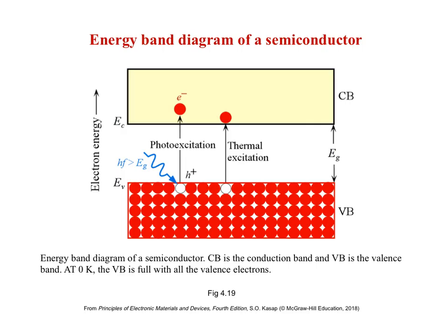the other. Conduction in a semiconductor requires either electrons in the conduction band or spaces in the valence band that allow redistribution of electrons in the valence band. In an intrinsic semiconductor, this can happen through photoexcitation or thermal excitation, where an electron from the valence band is brought above the band gap into the conduction band, but this requires the energy of the band gap for that electron excitation.